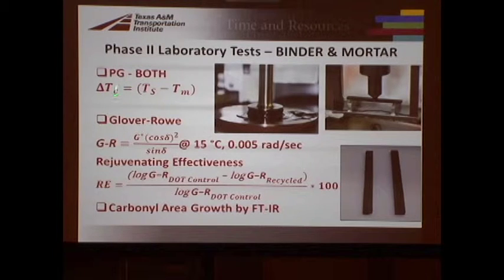We're also using a parameter that's gained a lot of attention recently called delta Tc. All that is is the temperature where the stiffness criterion in the BBR is met, minus the temperature where the m-value threshold is met. It's a good indication of embrittlement. Basically, you want to use base binders with recycled materials that are S controlled, so you want a positive delta Tc. But lots of binders that we use are m controlled, so their delta Tcs would be negative values.